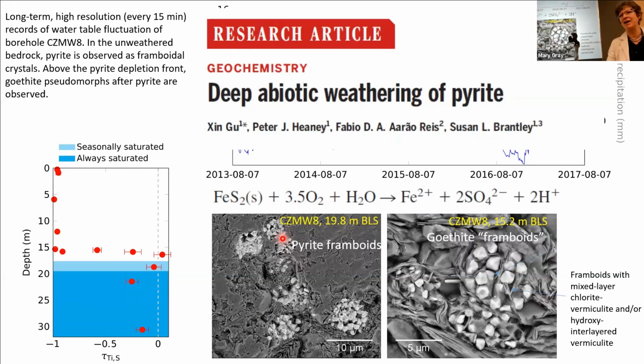So the paper that we wrote is deep abiotic weathering of pyrite. And the argument went like this. First of all, everyone assumes if you have pyrite oxidation, it's microbially oxidized. So we thought that's probably what would happen. We did hang little collectors, like tea bags of pyrite, down in our boreholes and then took them back into the lab. We worked with Eric Roden and Stephanie Napieralski, and she published a paper. There are iron oxidizers and sulfur oxidizers in the watershed, no surprise.